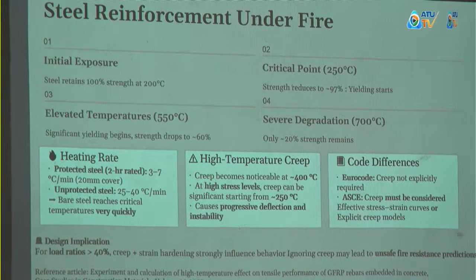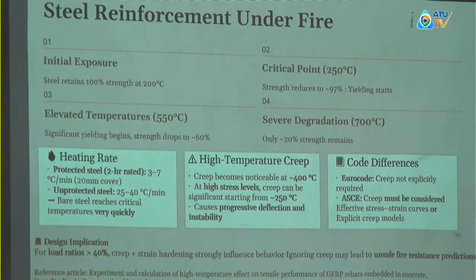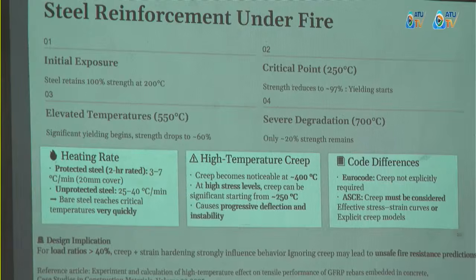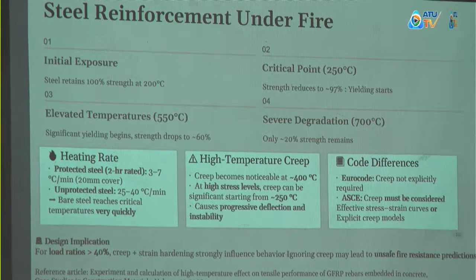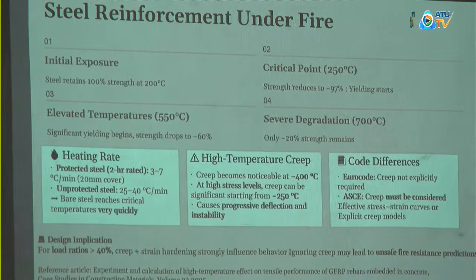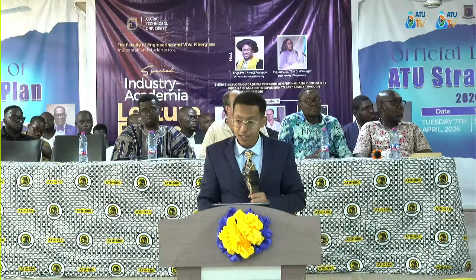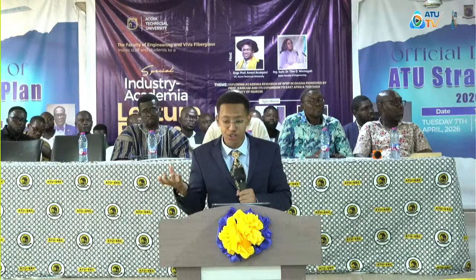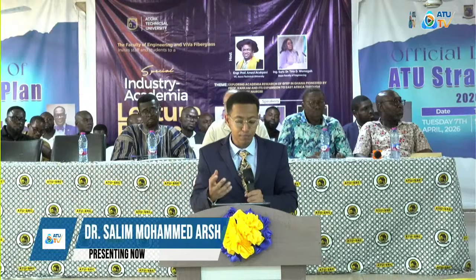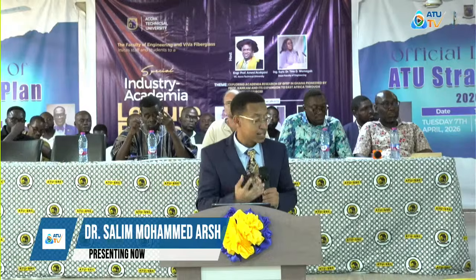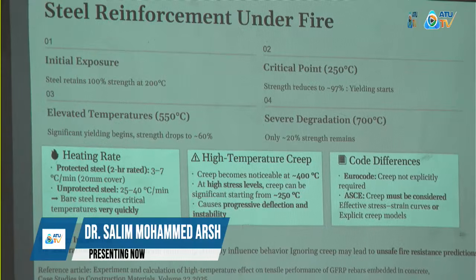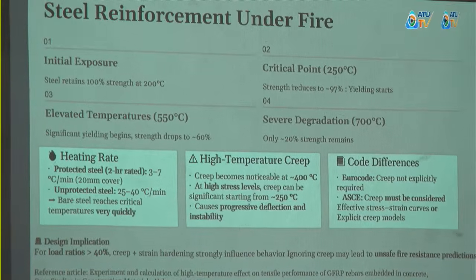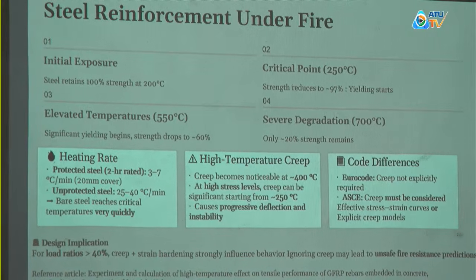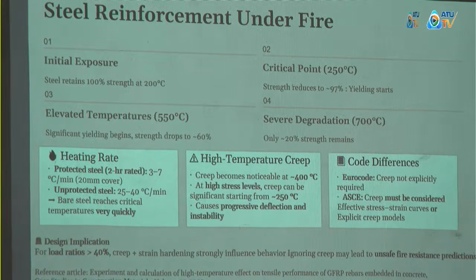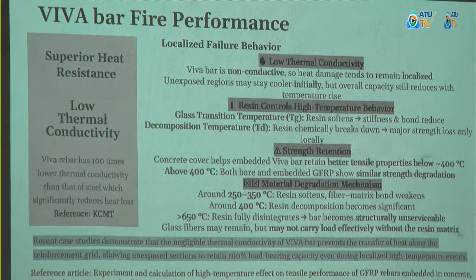And an important highlighted issue here is the thermal conductivity of steel that I also wanted to mention. You'll see it on a further slide. Steel transfers heat very effectively. This means that fire exposure on one region can affect reinforcement temperatures across a large structural area. So even the unexposed regions may weaken due to heat conduction of the reinforcement network, and you'll be able to see it visually in, I believe, the next two slides, and I'll be able to explain it better.